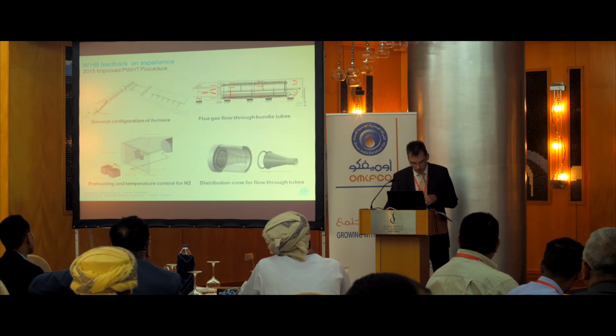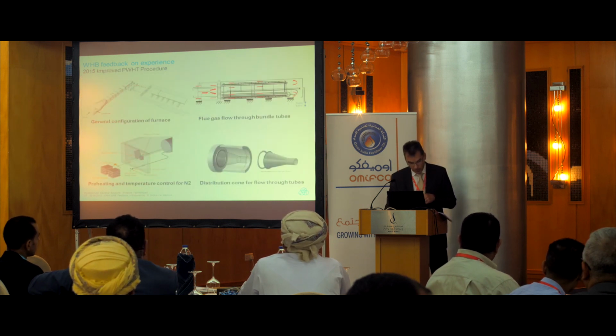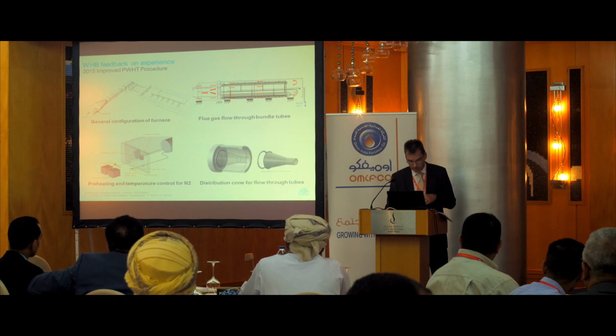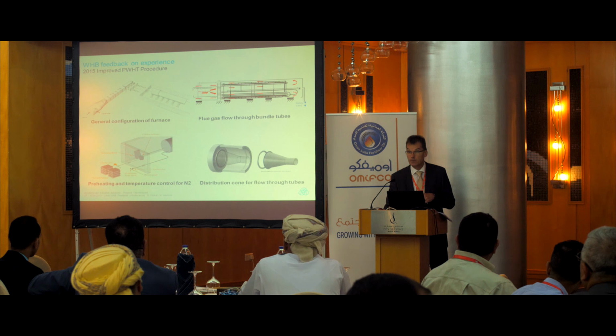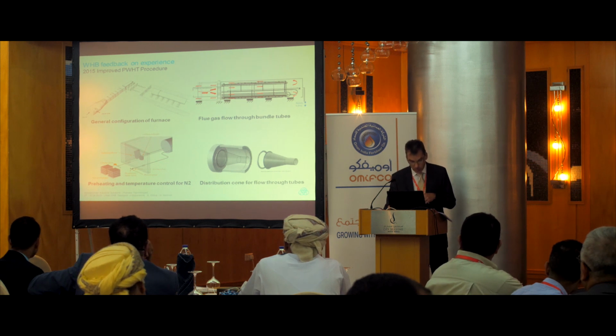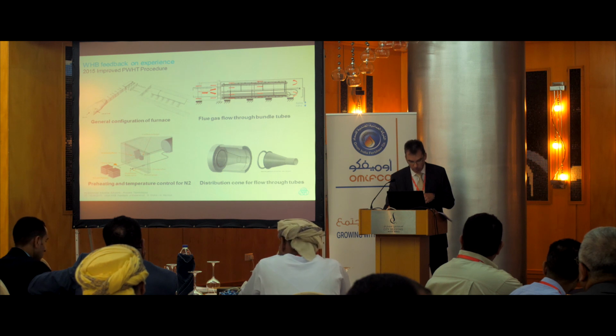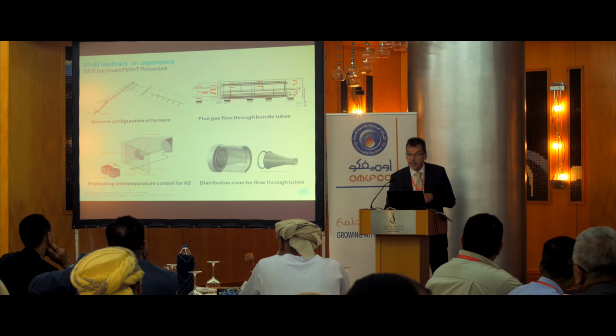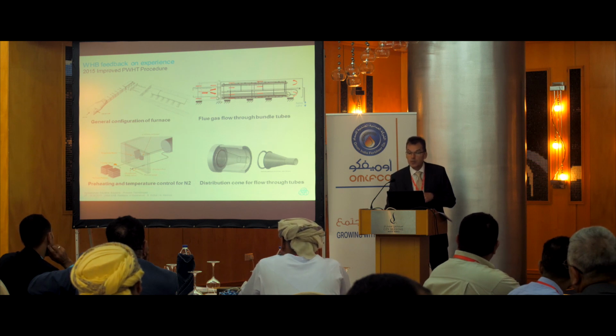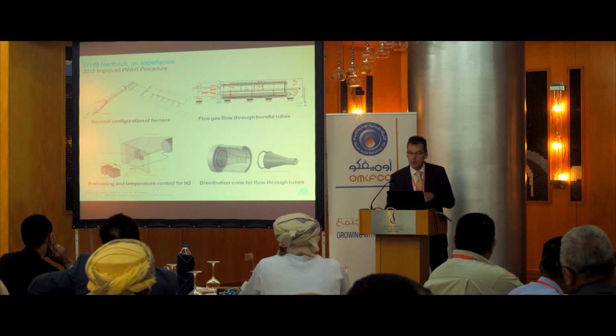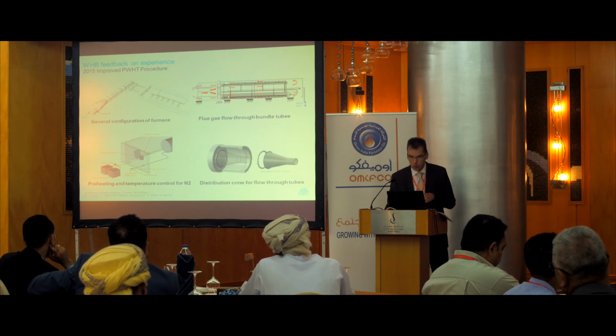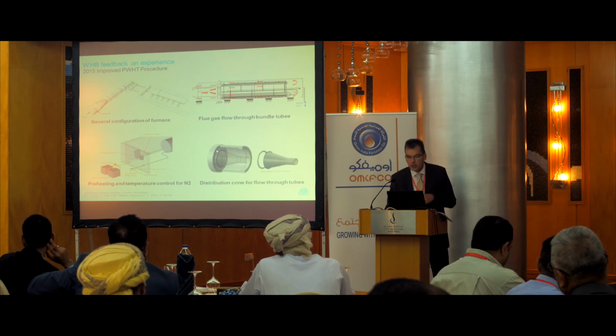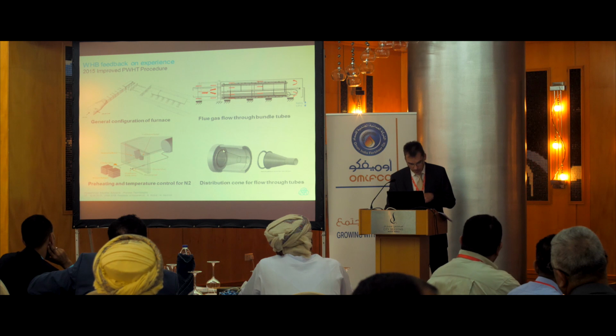Summarizing, for heat treatment, for all future fabrication, it was decided to accept only post-weld heat treatment with the whole bundle, including the auxiliary shell, inside the furnace. Furthermore, additional circulation of hot gas through the tube bundle is effected by a temporary internal cone in the channel. We also changed the heat treatment so that hot gas also goes inside the U-tubes, so that we have a uniform heat distribution outside the bundle and in the tubes. Therefore, we have this cone put in front of the tube bundle.